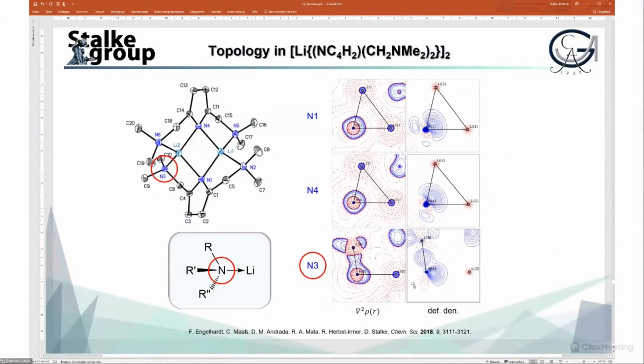But amazingly, the donor bond from the lithium, from the side arms, for all four of them, they don't differentiate that much from the amide bonds. So they are a bit more structured, a bit more directed towards lithium, not that diffuse. However, they have to share two lithiums, and that one is only addressing one lithium. That contracts the density, of course.